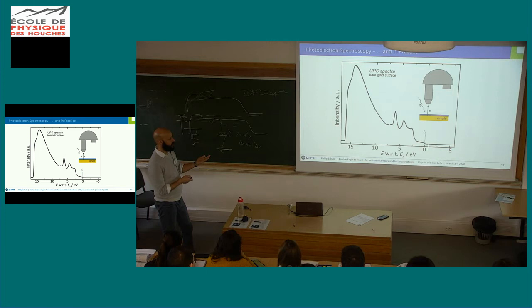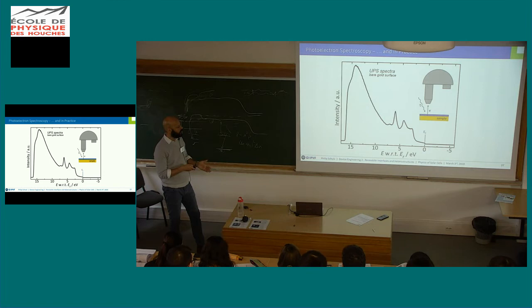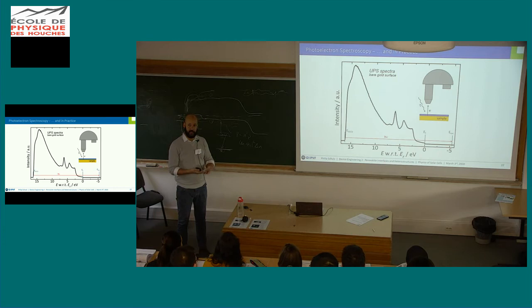So this is where we align our spectra to, so its energy axis, binding energy, with respect to the Fermi level. This can also be referenced, for instance, to the vacuum level. And then here on this end, we have the secondary electron cutoff. When we measure this, we now project the excitation energy on this, and we can deduce the vacuum level at this energy here, which would correspond to 5.1 eV binding energy, which is what you find for polycrystalline gold surfaces that are sputter clean in vacuum.